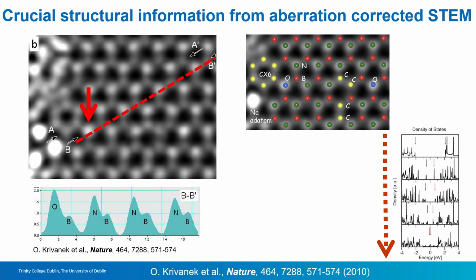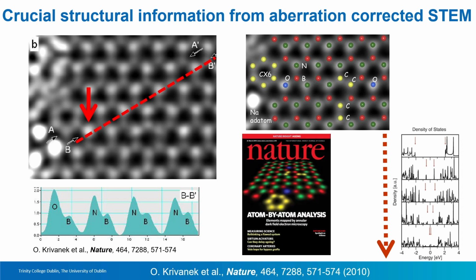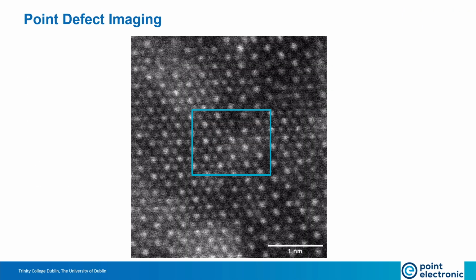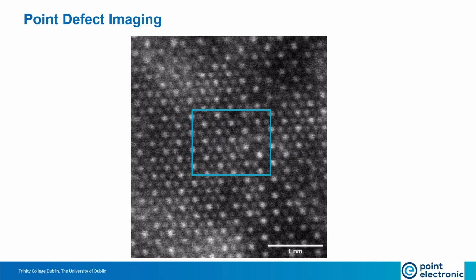We also learned that carbon atoms always replace pairs of boron and nitrogen, while oxygen always replaces nitrogen atoms. If you dope more and more with carbon, you actually close the band gap. So from a wide band gap semiconductor, typically an insulator, boron nitride, you can close the band gap quite substantially. This was done for the first time back in 2010, and was quite a unique characterization tool that we developed. We also look at very defective areas.